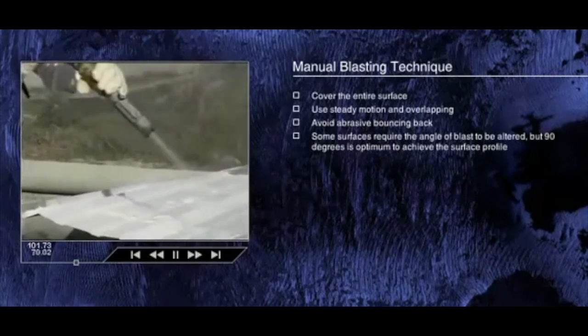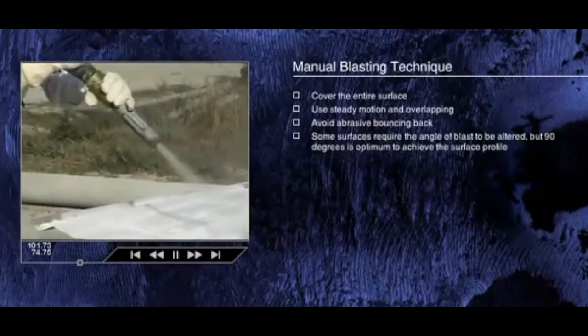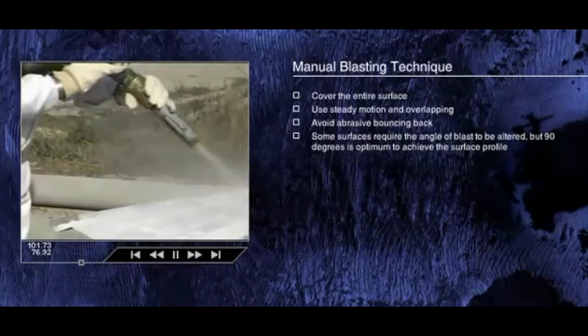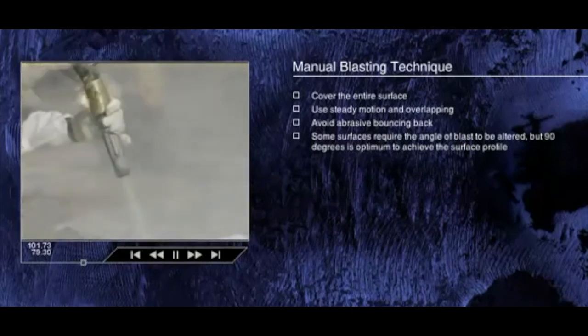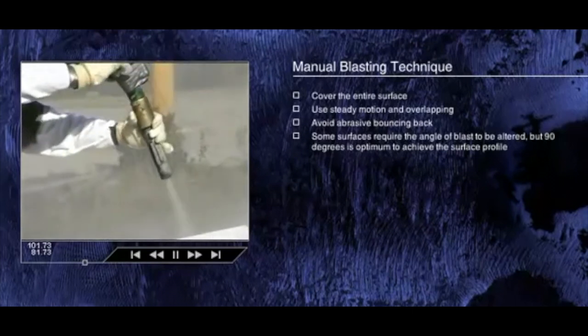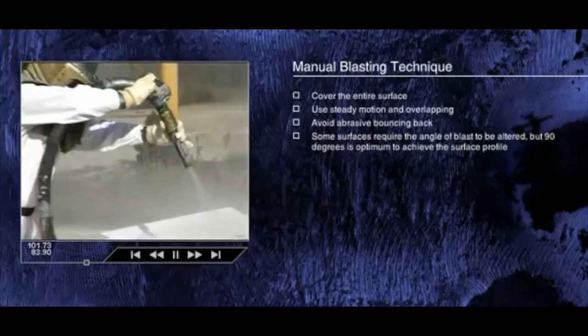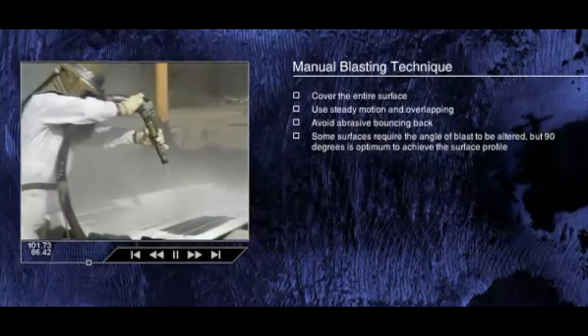The operator must be aware that this technique, while efficiently removing the existing coating layer, produces a reduced surface profile due to the angle of impact. Final blasting at right angles to the surface is required if the correct surface profile is to be achieved. Speed of nozzle traverse is dictated by rate of cleaning and should be as fast as will clean thoroughly without unnecessary dwell.